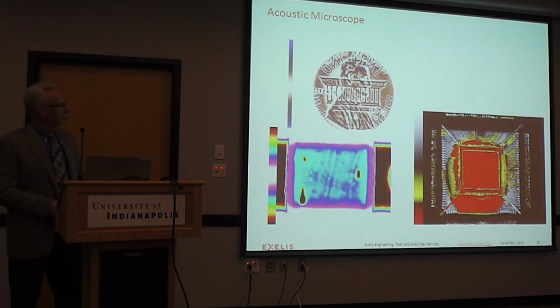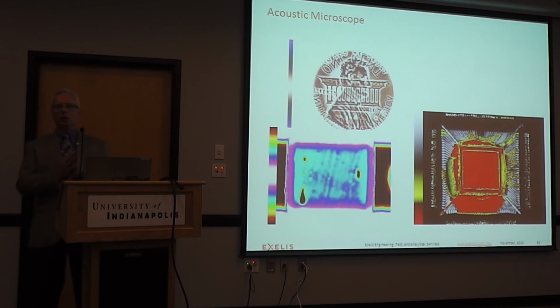These are some acoustic images showing, in this case, fractures in a power transistor beryllium oxide substrate. And this is an IC that has gone through popcorning. What is popcorning? That's where the plastic package on an IC delaminates from the silicon die, and you end up with pulled up bond wires. It can be really catastrophic in its effects. This red area is an area of delamination, so scanning acoustic microscopy can be used to image what ought to be a solid object, and detect voids and delamination and cracks and things like that.